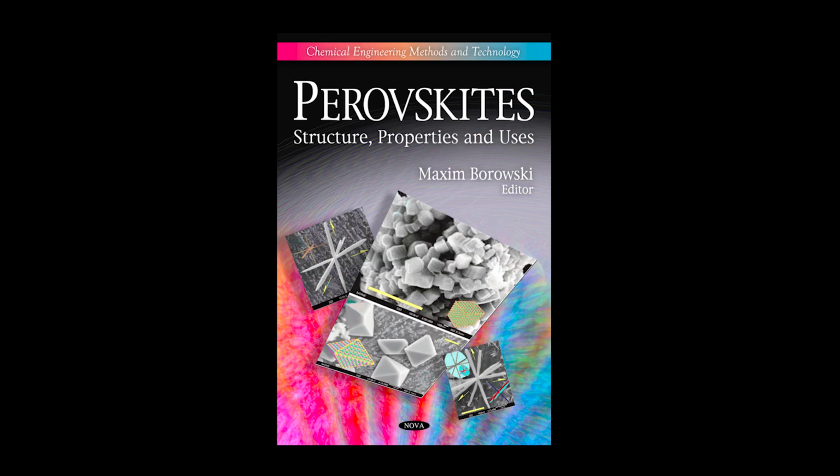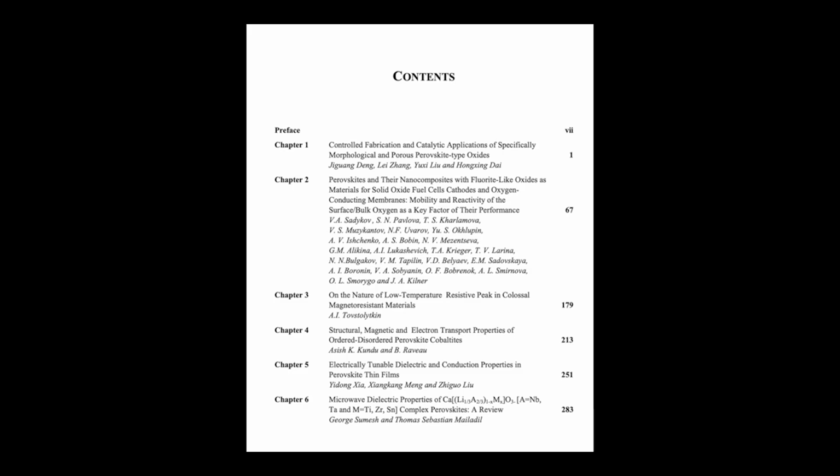First, you absolutely must have the physical site for the reaction to occur. This typically requires the presence of an oxygen vacancy, VO, on the catalyst surface. This vacancy acts as a site to absorb oxygen or one of the reactants, initiating the process. Second, and just as vital, the B site cation within the perovskite must be able to undergo an easily proceeding full redox cycle. This means there has to be efficient electron transfer between the reactant molecules and the catalyst. For example, the B site cation, say B^n+, must be easily reduced to B^(n-1)+ by accepting an electron from a reactant and then readily oxidized back to B^n+ by giving an electron to another reactant like oxygen. That cycle is essential for turnover.